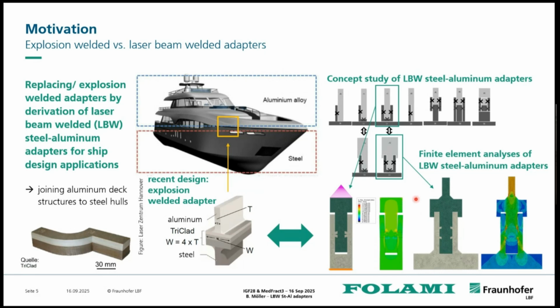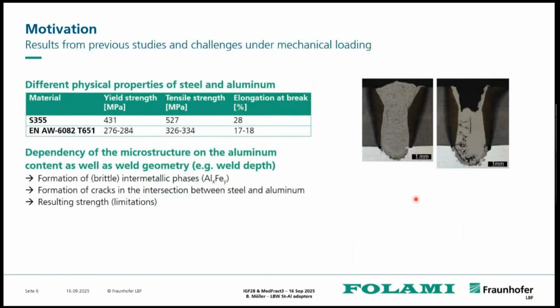However, I will first start here with a basic investigation. So we know that we have two very different materials when we try to join steel to aluminum. In this specific case, we joined S355, which is relevant for the shipbuilding industry, at least in terms of strength, and the corresponding aluminum material was EN AW 6082, so aluminum alloy 6082 in heat-treated state. Already from the yield strength, tensile strength, and elongation, we see that they are quite different materials, but also in terms of heat transfer, these materials are quite different.